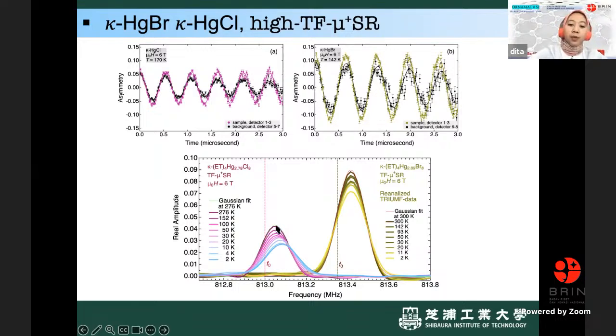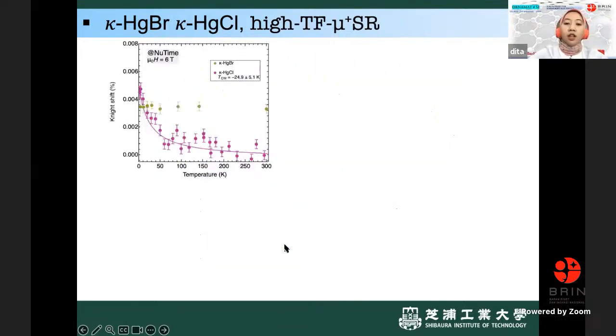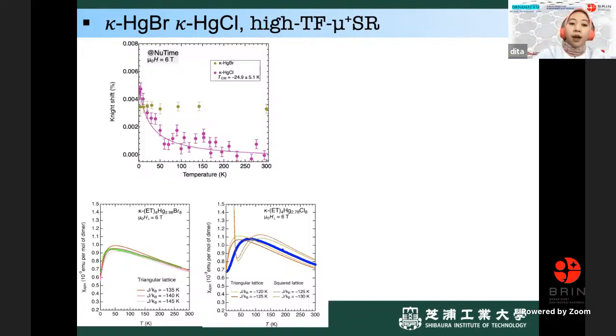Okay, so the peak here shifted to the right side. If I plot it, it should be like this. For the chlorine, there is a gradual shift by lowering temperature, but for the bromine, it's barely changed. Then we can compare the situation of the Knight shift and the susceptibility that we have.